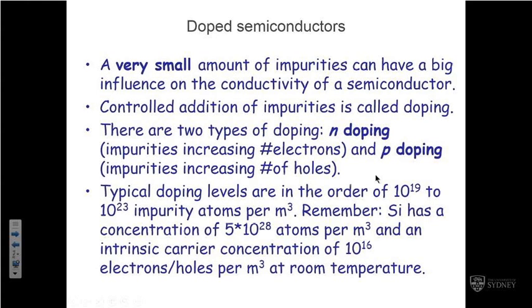And remember that silicon has a concentration of about 5 times 10^28 atoms per meter cubed. So that gives you an order of magnitude comparison of how many impurities you'll have per how many atoms of your native species. Typical values for intrinsic carrier concentrations are about 10^16 electrons and holes per meter cubed. The intrinsic carriers are, remember, the ones that exist there already and contribute to a background conductivity. So these are normal kinds of numbers.